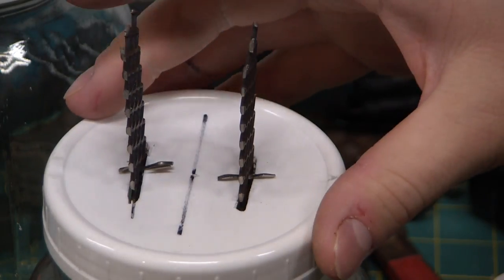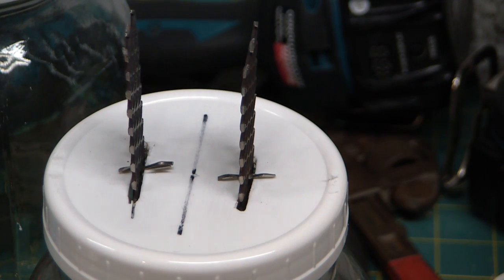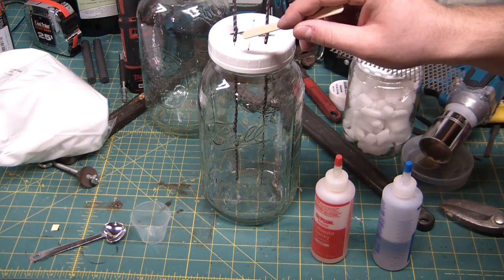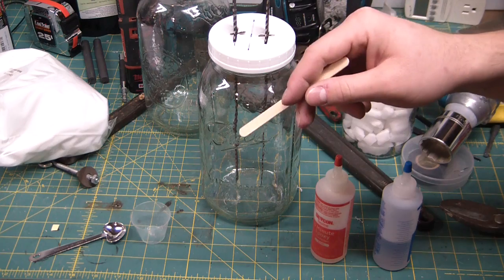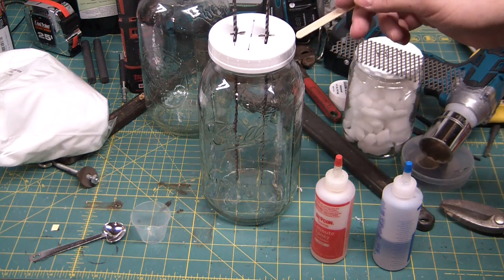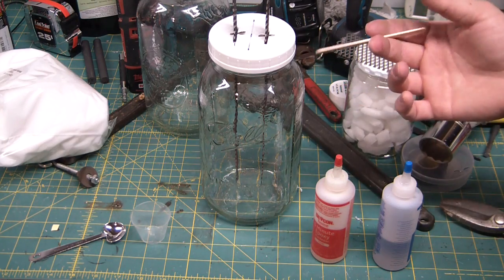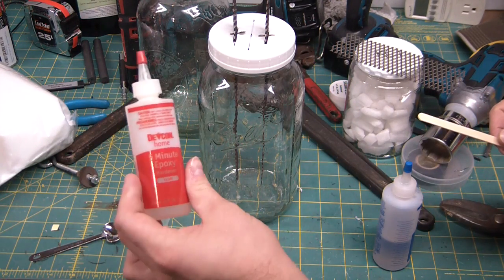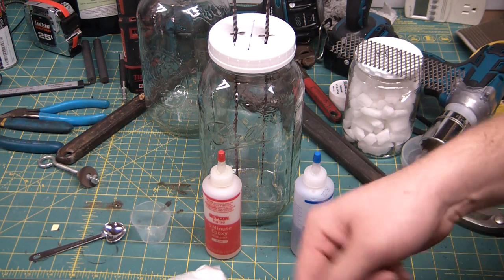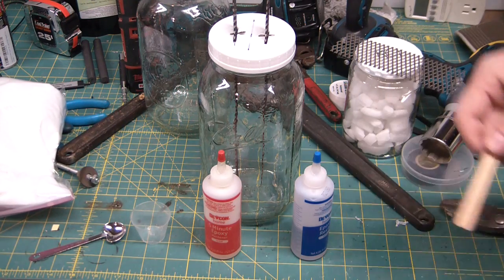So to hold the electrodes in place while I get ready to glue them up, I just cut off a couple little pieces of this super cheap titanium sheet I got off eBay. It's actually real titanium, I spark tested it. I'm using that to hold these nice and center. So I was planning on using JB weld to fill this gap, but I remembered JB weld does have steel in it, like powdered steel added to the resin. Odds are eventually that would be eaten through because this is a nasty corrosive environment. Instead I'm gonna use some of this cheap Devcon five minute epoxy and I'm gonna add some fumed silica to it just to thicken it up. So one, it doesn't go through there and two, this is essentially very lightweight glass, so it should act as a pretty resistant additive for the harsh environment that it's going to be in.